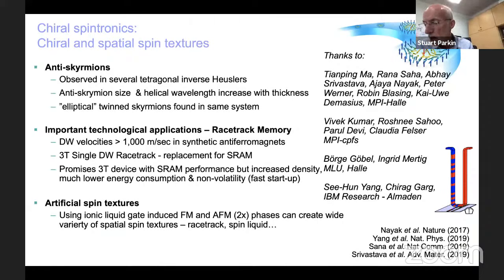You change the sign of the anomalous Hall effect. But interestingly, the spin Hall effect does not depend on the chirality. This is something that we first pointed out in the manganese-3 iridium cubic system. Therefore, both chiralities are possible, but the spin Hall effect related to that chiral structure is independent of the chirality, so we can observe it. And we actually observed it. We were the first to observe it in a chiral antiferromagnet, in manganese-3 iridium.